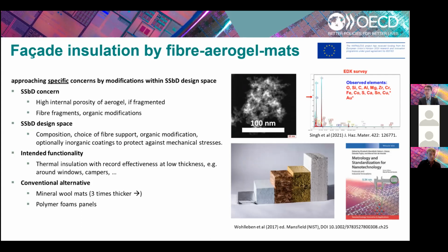And the aerogel material is already on the market, but at a relatively smaller scale, but it is a commercial product. And it allows, that's the advantage of the material due to the high porosity, to suppress the thermal transport by the gases. And so you achieve a better insulating power at a lower thickness of the insulating material.